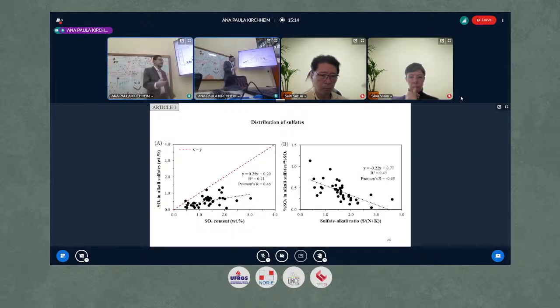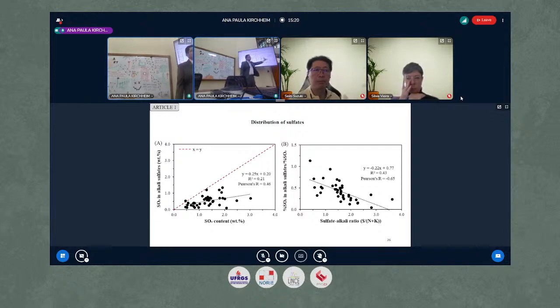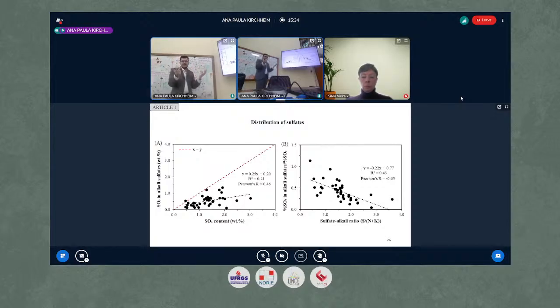If you look more closely, we see that increasing the sulfate alkali ratio decreases the percentage of the sulfate present as alkali sulfate. This means that if we don't have enough alkali to react with the sulfate, the excess sulfate that doesn't volatilize in the kiln will be incorporated in the main clinker phases, especially alite and mainly belite.